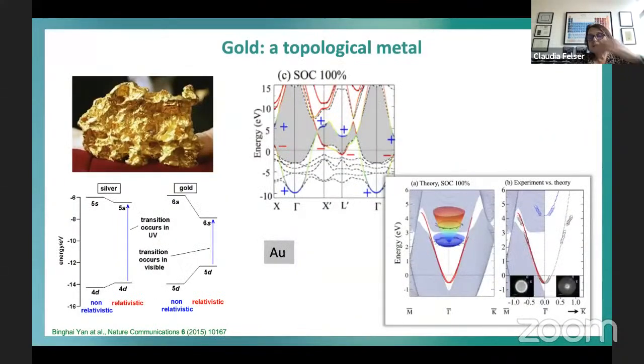This is a super common phenomenon—it's also shown that more or less the color of gold can now be explained by topology, because you can simply say it's different from silver. Here you see the schematic electronic structure of silver, non-relativistic versus relativistic. In gold, the 6s electrons are much more contracted versus the 5d electrons. Therefore, the transition between 5d and 6s is much smaller than in silver.